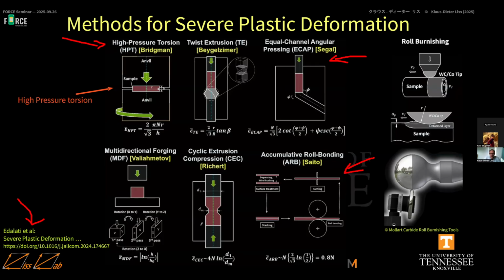And it shows not just this one page of severe plastic deformation. There are multiple pages, like 5 or 6 pages, including roll burnishing. Roll burnishing has, for example, an application for making the surfaces hard. So what we do is severe plastic deformation at the surface, which is basically very similar to what we do in the bulk in HPT or ECAP, done on the surface in a thin layer, making the surface hard and resistant, corrosion resistant, stress resistant, and so on.